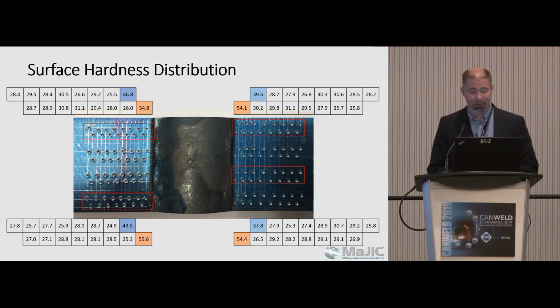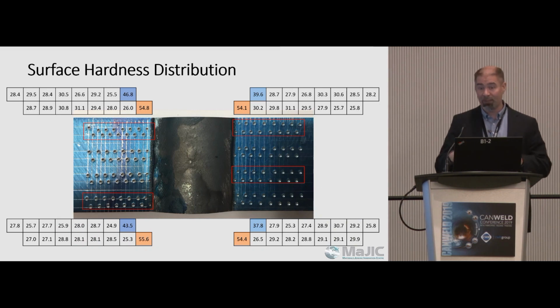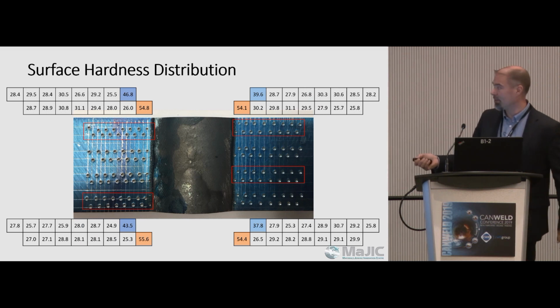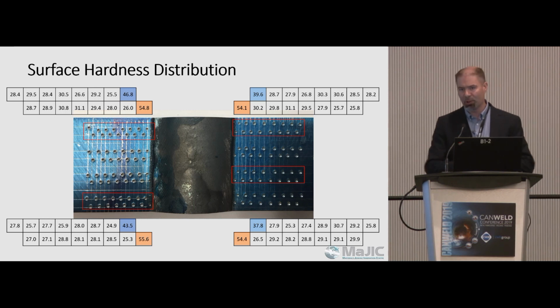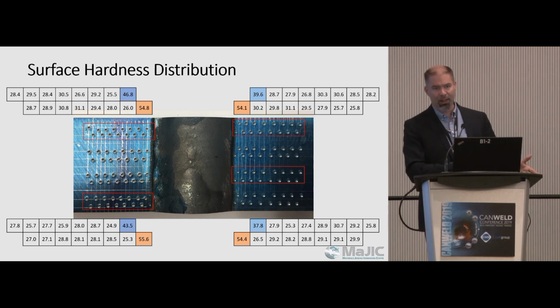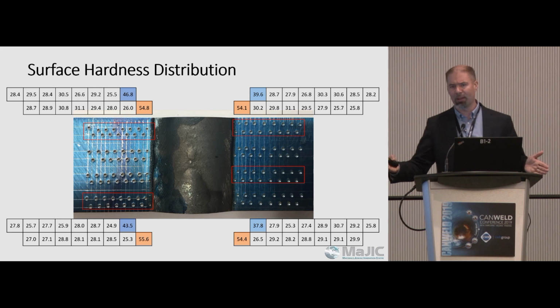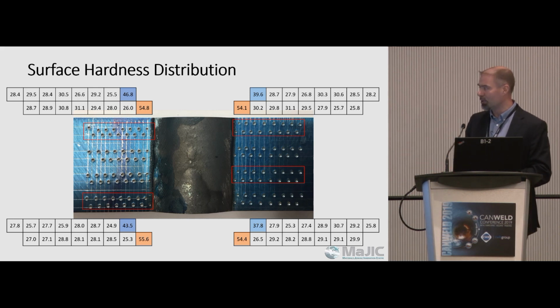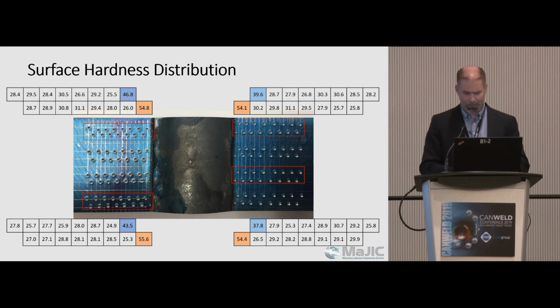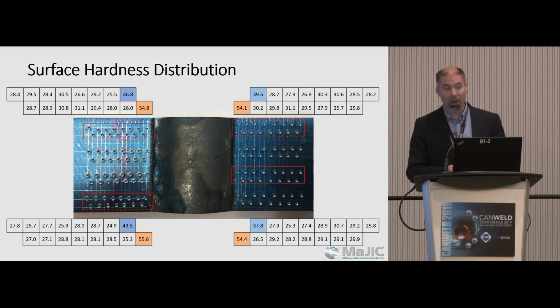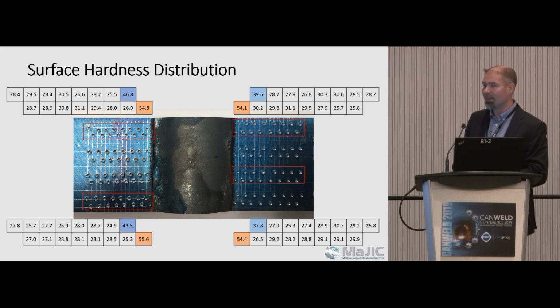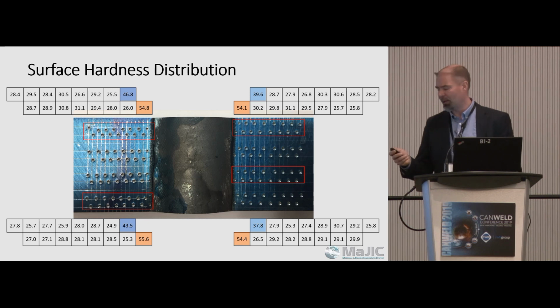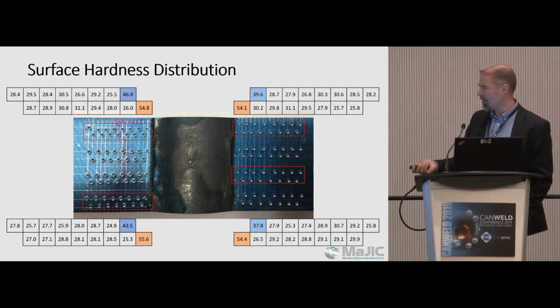So this is what the surface hardness distribution looked like. So this is a top view of the weld. Maybe not obviously, but that's the weld bead. And these are all the hardness indentations from the fusion line out. And as you can see, not surprising, really close to the weld, it's hard. And as we move away from the weld, the hardness returns closer to the original base metal hardness. Unfortunately, using Rockwell C, we're really not getting a highly dense measurement of these hardness points. So again, that's an area for improvement going forward.